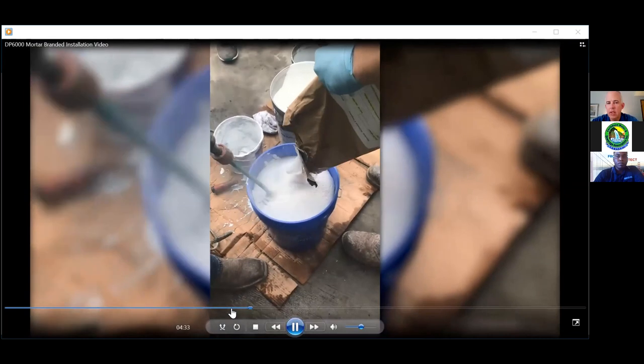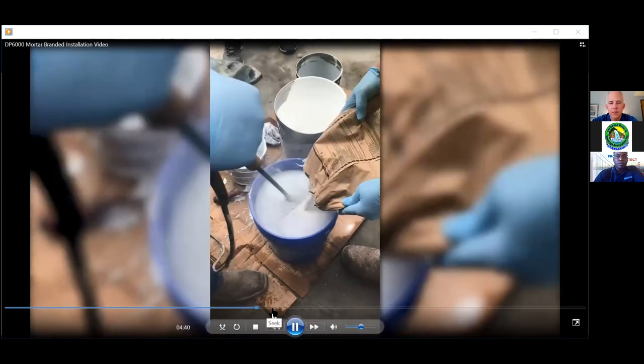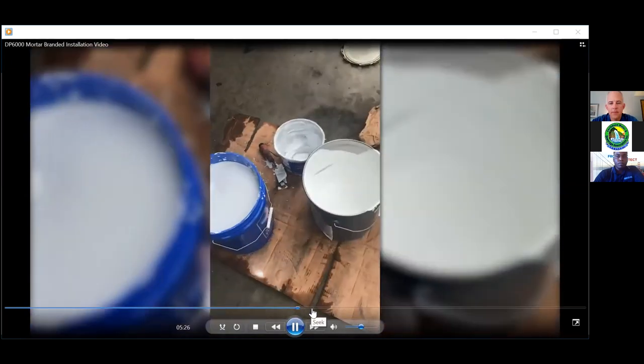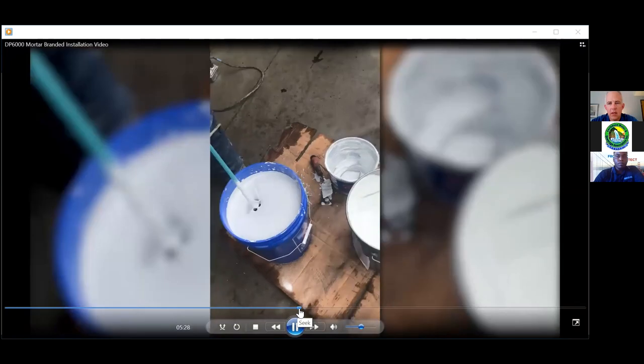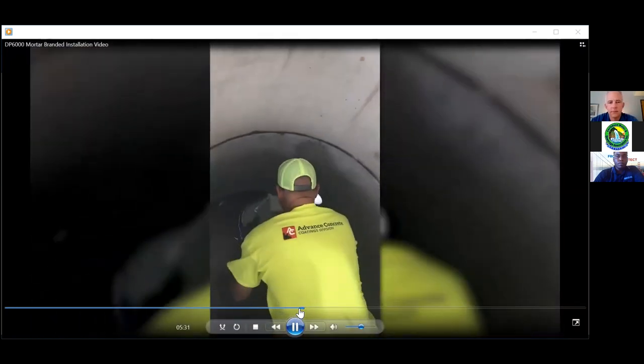On a lot of smaller structures, it's a whole lot simpler to hand trowel the material in place. And that's what they're getting ready to do by adding this aggregate into that epoxy resin. I'll fast forward on through it a little bit. Again, he's just drill mixing everything up thoroughly. And now he's getting ready to start the application process. And as you can see, what he's troweling on there is about an eighth of an inch thick.